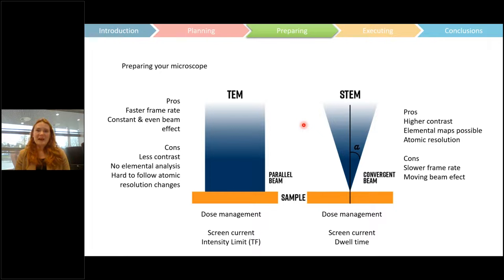There is, of course, I think in the in situ world, a bit of an argument about what's better, TEM or STEM mode for in situ experiments. Both have their pros and cons. The pros for TEM mode is obviously you can get faster frame rates. You can image much quicker, so you can get better time resolution on your reactions. And you have a beam effect that's not moving. It's a constant, even beam effect. So if you do have a beam effect, at least it's not changing.